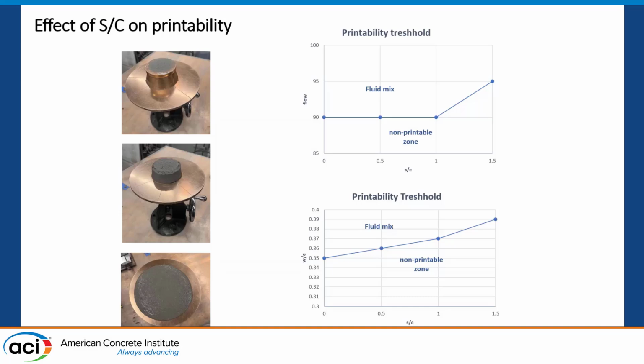And again, for example, one approach to design the mix is that we simply can use a classical flow table, and we can easily distinguish the printable mix from a non-printable mix. And with 3D printing, you don't have that much freedom anymore. You have a very narrow band of compositions which can be extrudable and which can be deposited. And these are classical mixes. You don't have any chemical admixtures. You don't have viscosity modifiers here, just simply regular mortar. And basically, these mortars are a little bit richer than the classical ASTM test we do for compressive test or for the classical flow table test. So again, those are the approaches we can use to test the material.